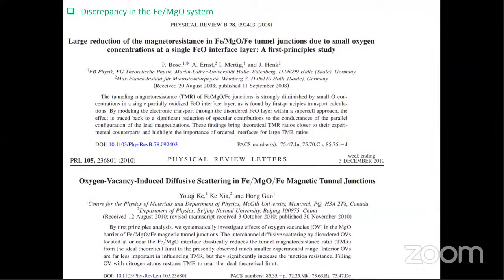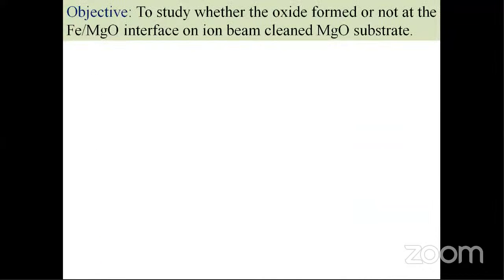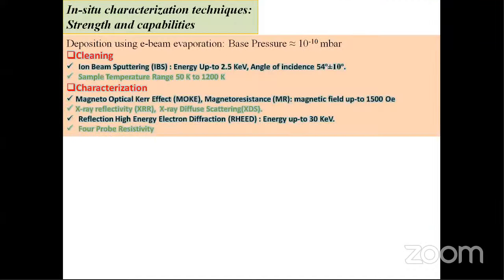For cleaning, we have an ion beam sputtering with energy up to 2.5 kV, and sample temperature we can go from 50 Kelvin to 1200 Kelvin. For magnetic characterization, we have magneto-optical Kerr effect and magnetoresistance. And for structure characterization, X-ray reflectivity, X-ray diffuse scattering along with reflection high energy electron diffraction. And for transport measurement, we also have four probe resistivity.